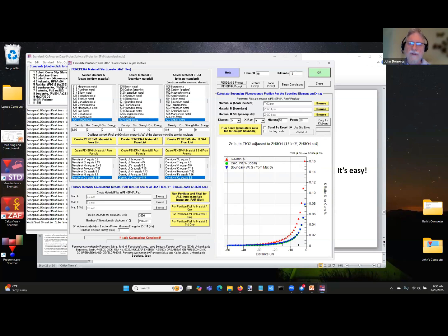And if we actually increase the energy, because we want to get good sensitivity, we want to really zap the sample, it actually gets worse. It goes from 800 ppm, I think, to about 1,000 ppm. Let's see what it does here. Yeah, up to 1,000 ppm. So, model it.